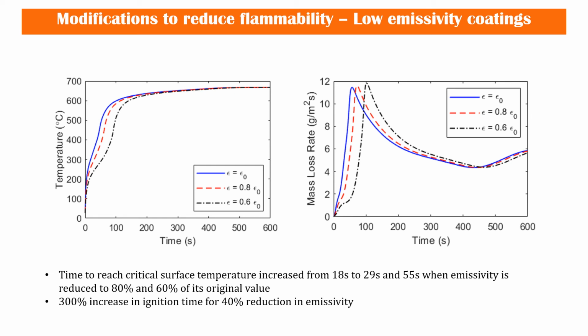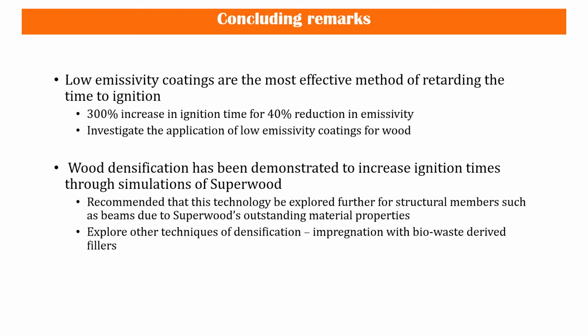This type of coating is used in the construction industry to produce low emissivity glass. For a facade application, the lifetime of coating in an outdoor environment must be considered, as rain and moisture may degrade the coating. It is recommended that the application of low emissivity coatings to wood is investigated, as the results of this study indicate a 300% increase in ignition time for a 40% reduction in emissivity.